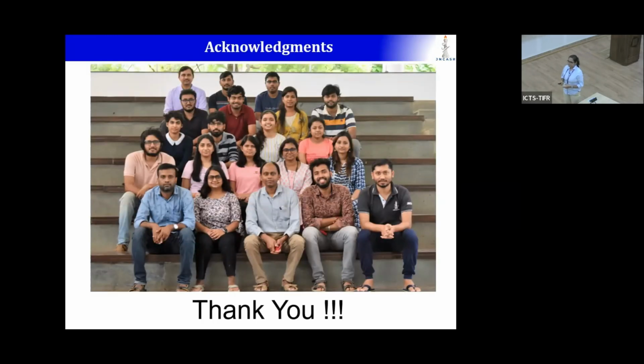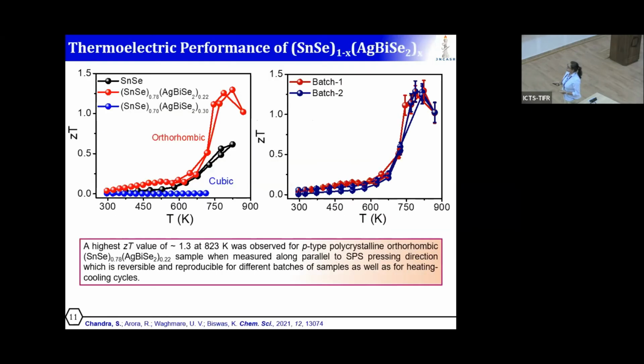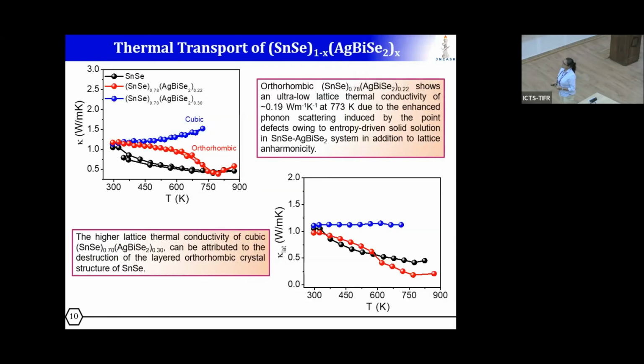My question was regarding the thermal conductivity in the cubic phase. It seems that with increasing temperature, it increases. That shouldn't be the case, right? I understand the other two are decreasing because of phonons. Yeah, so here the layered crystal structure is destroyed for the cubic sample. The phonon damping happens in the orthorhombic system because of the layers and the tin 5s2 lone pair. But because here tin, silver, bismuth are occupying the same cationic position and it's a disordered structure, we don't have that sort of anharmonicity. So the phonon scattering is not that effective, and electronic thermal conductivity is playing the major role.